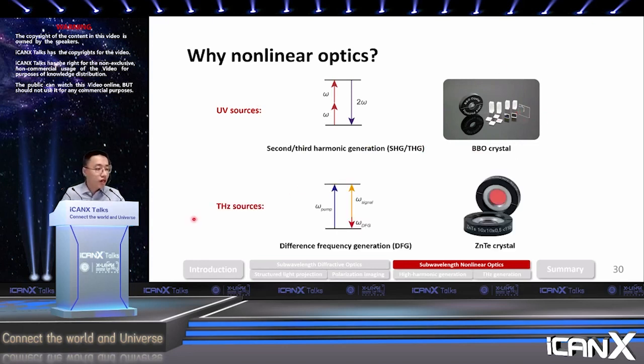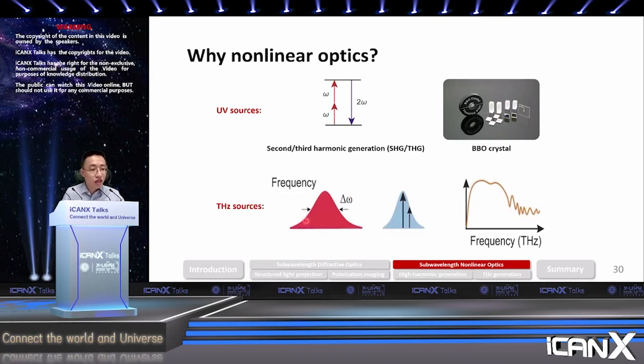If you want a broadband terahertz source, you can use the difference frequency generation process. If you have two infrared laser beams with slightly different angular frequencies, through DFG you may get a light signal with a relatively low photon energy in the terahertz domain. For example, if you shine a femtosecond laser onto a nonlinear zinc telluride crystal, through intrapulse difference frequency generation, you may get broadband terahertz emission.